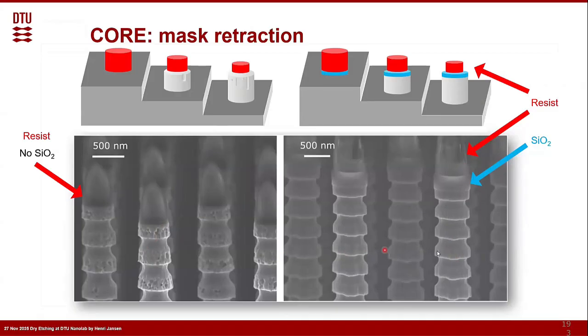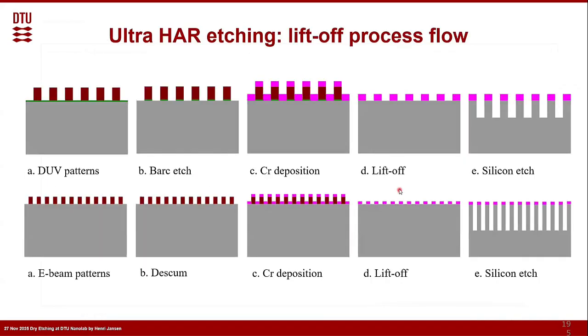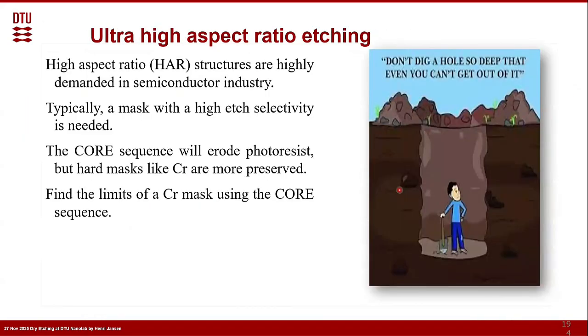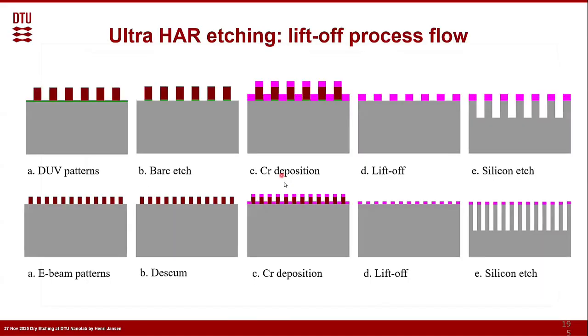So this is the same process running, but here there was a protective layer. But even silicon oxide has its limits, maybe the selectivity is 20. It doesn't retract like photoresist, but it's still getting thinner, and after a while it would also be a no-go. So therefore, we would like to look at other hard masks, and for instance, that's chromium, which can have much higher selectivity.